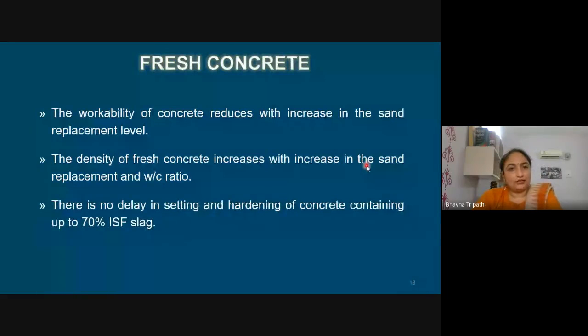Now, I'll start the discussion about all the properties of concrete one by one. The workability, I'm not showing the results of workability because largely we had controlled workability. The reason is that we have to keep one parameter changing so that we can compare all the mixes. Therefore, workability we had controlled and maintained uniform by adding superplasticizer. The reason was that with addition of ISF slag, the workability was observed to decrease. So to maintain workability of each of the mixes, we had added sufficient quantity of plasticizer, that was a PC based third generation plasticizer.